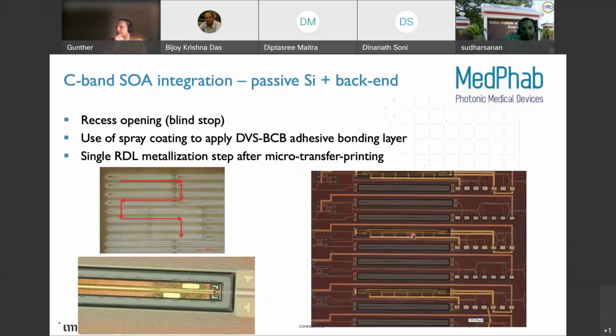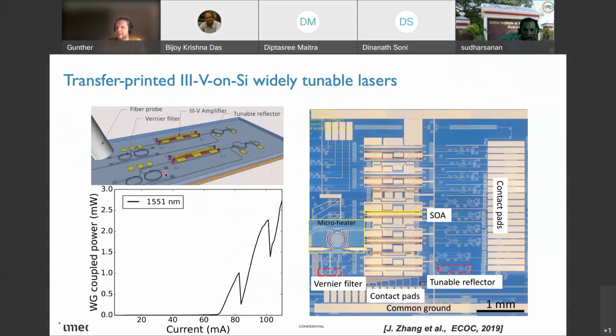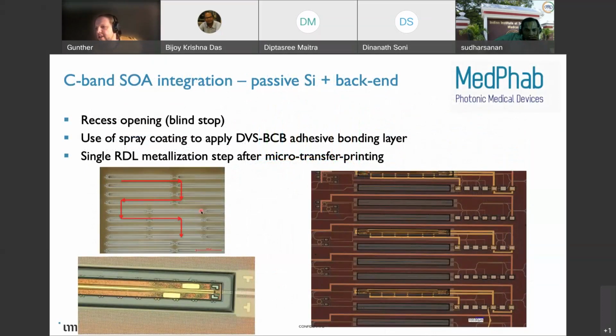Since then, we have worked further on this technique. In this case, we started off with a simple passive circuit. We printed the SOAs, and then we did post-processing of the heaters. Now, this post-processing of the heaters is something you would like to avoid, and you would like to do that before you integrate the III-V SOAs. That's illustrated here, where now we are processing the silicon and the heaters up front. We're then etching cavities in the back end, and we are printing the III-V component in that cavity.